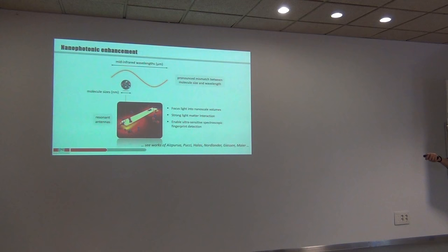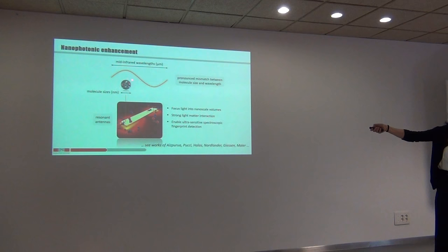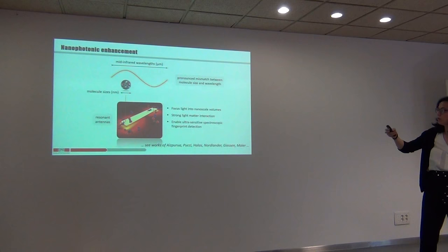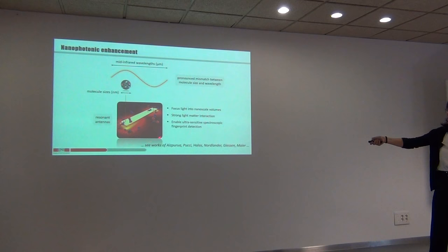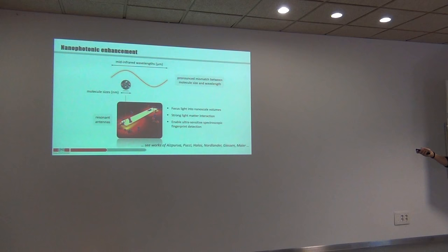This is where we think as a community that nanophotonics can actually help to overcome some of these challenges. One reason the sensitivity is low is that you have this mid-IR wavelength on the order of 5 to 6 microns, and if you have molecules on the order of 10 nanometers, there is a significant size mismatch — the radiation is too long and the molecule is too small. This is where we can use near-field enhancements in small-scale volumes to confine the light even more, so that we can have pretty strong light-matter interaction. This has been started to be explored within the mid-IR spectral range, and there are various people who have been contributing to this field.